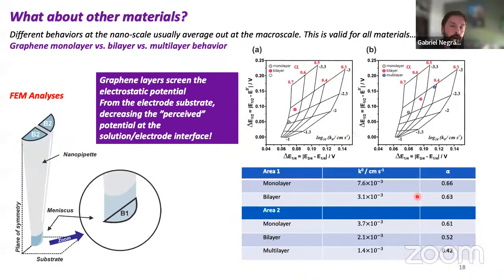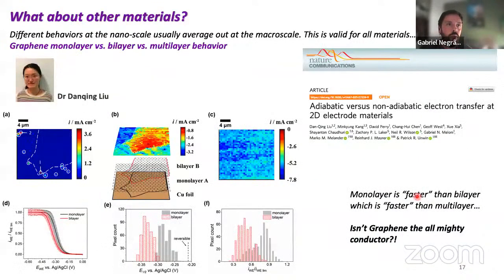And this, I think, has a nice implication in the electrochemistry field, because now I understand it's kind of adiabatic versus non-adiabatic electron transfer in graphene. We pin down what's happening, but there are practical applications as well, because of course it's impossible to have a single layer of graphene that's as large as it takes for making a supercapacitor, but there's an impact from the amount of multilayers or bilayers they have. So we have to bear that in mind and engineer materials properly, because this affects the properties quite a lot. And once more, we would not be able to see that if it weren't for those techniques that can do electrochemistry resolved in space.